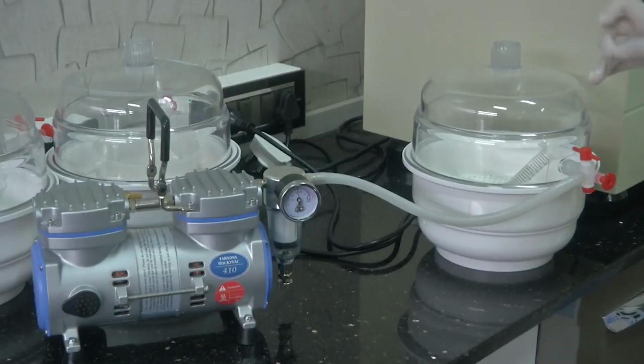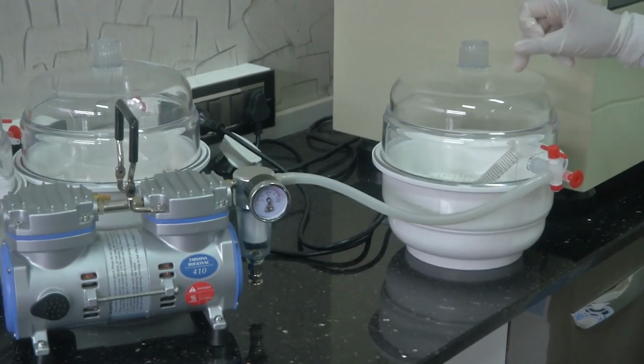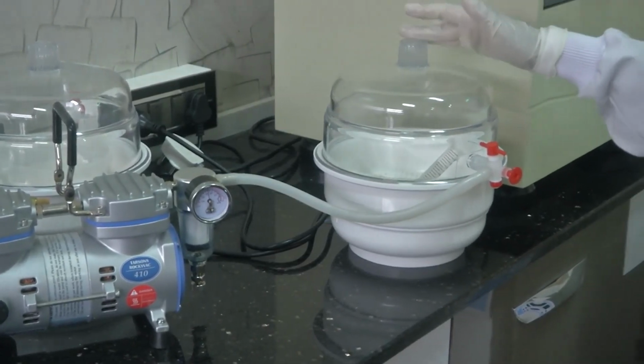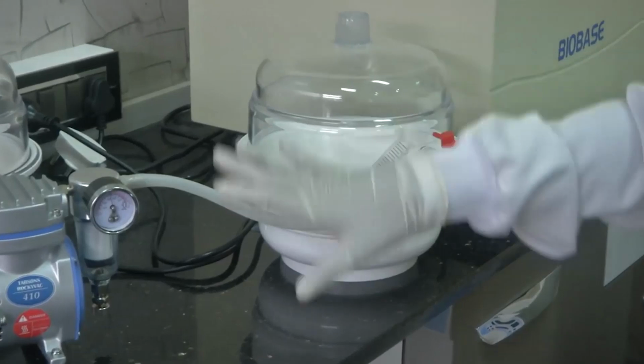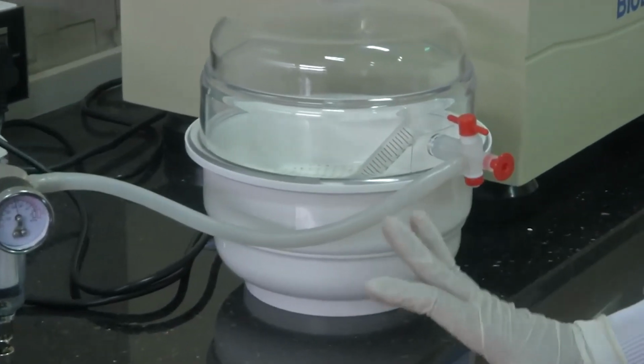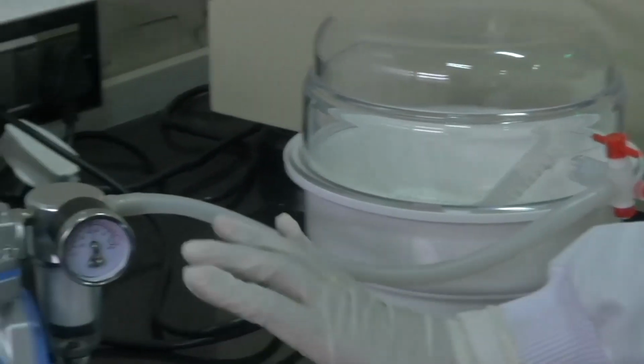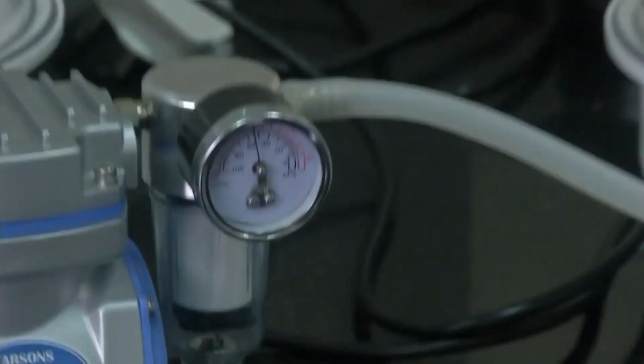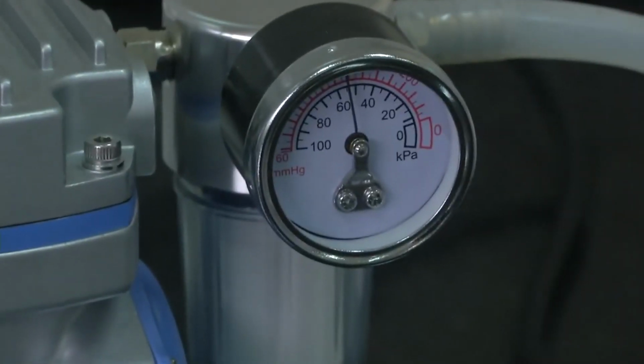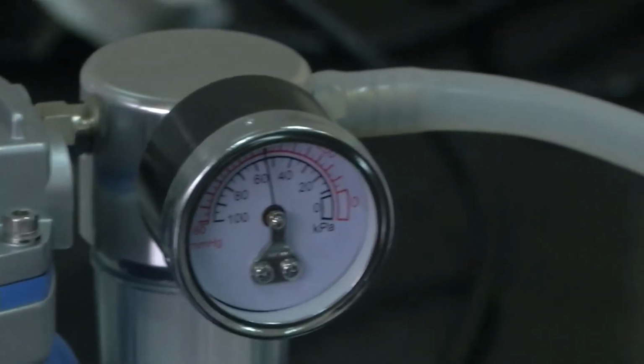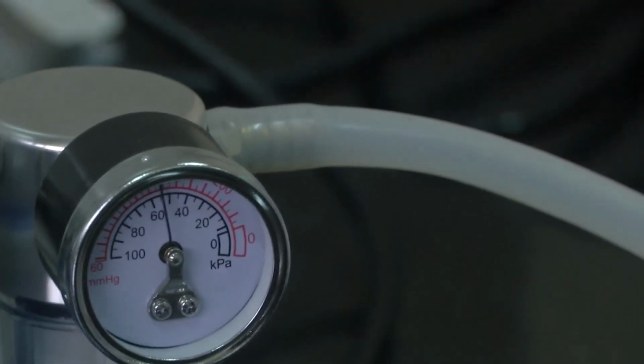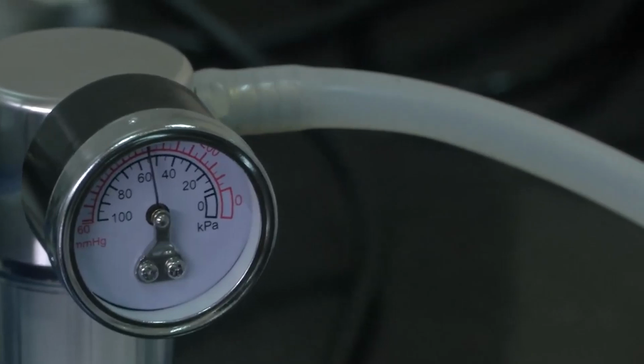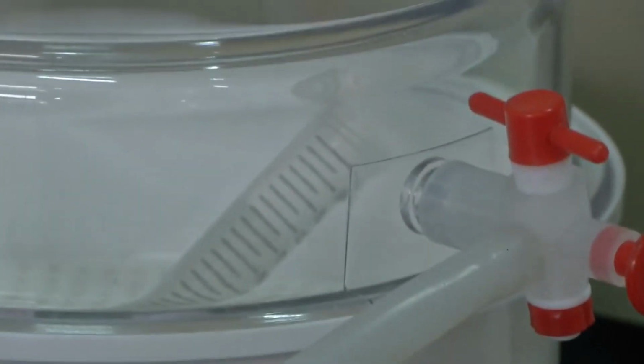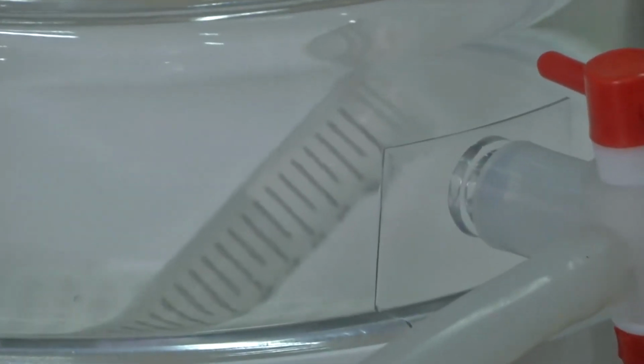So, now the container where I had the elastomer is placed inside the chamber, and the vacuum process is going on. As you can see, there is some amount of pressure, that is, the vacuum is being created inside this desiccator. I am not sure if you can see inside how the bubbles are coming towards the top of the surface. So, there are a lot of bubbles in the beginning.